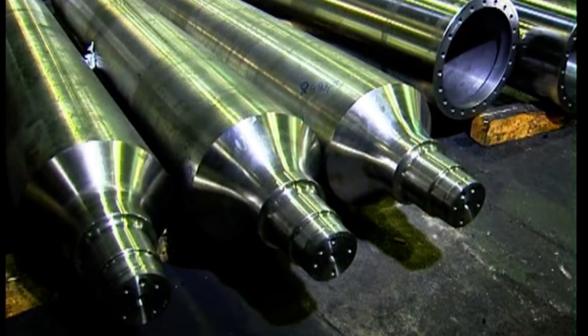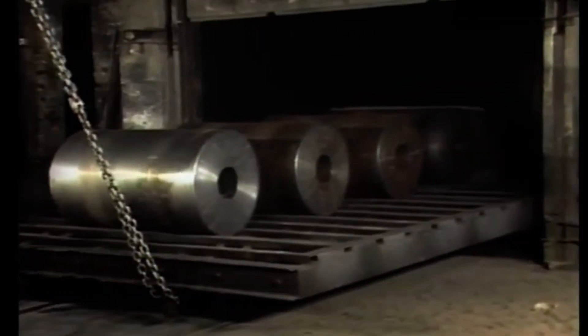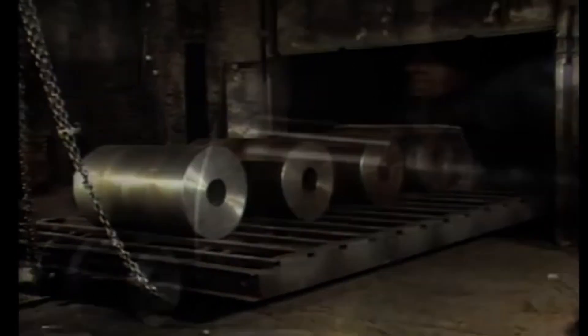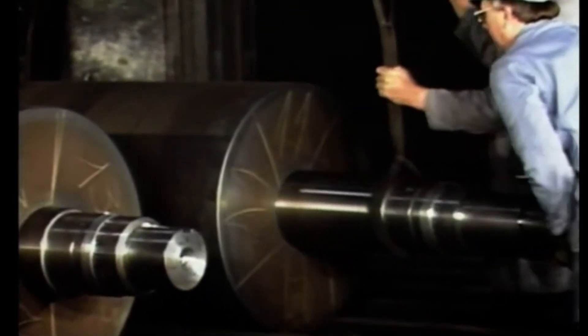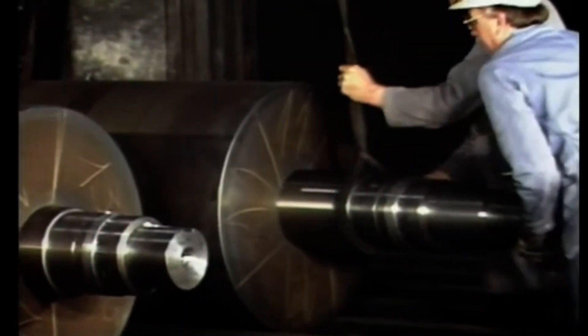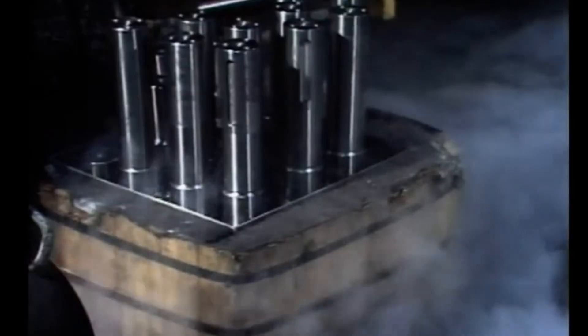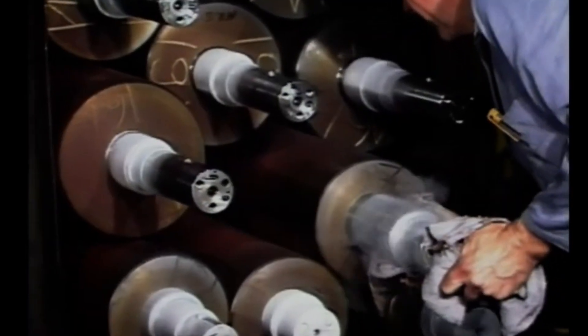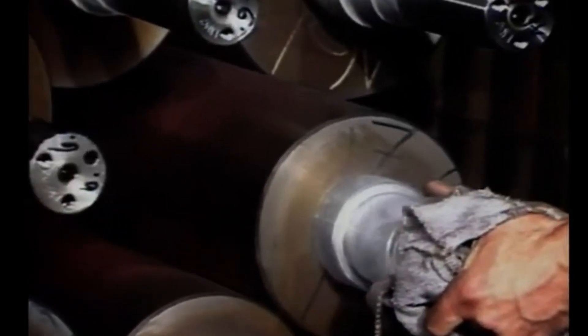What about rollers with steel shafts? How are they attached? For example, gray cast iron rollers are fitted with steel shafts while still warm after heat treatment. Once cooled, the material contracts around the shaft, creating a permanent, inseparable unit. In some cases, steel shafts are cooled to minus 65 degrees Celsius before being press-fitted into the cast roller body, ensuring a tight and lasting connection.